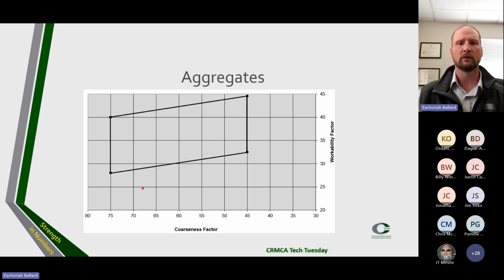James Shilstone revealed a mixture design process based on the proportioning of aggregates using a combined gradation to a proportion of group of sieve sizes that can be categorized as coarse, intermediate, and fine. He designed a chart to proportioning equations from about 20 mixed designs based in Saudi Arabia, and confirmed the chart and equations using aggregates from the Dallas, Texas area.